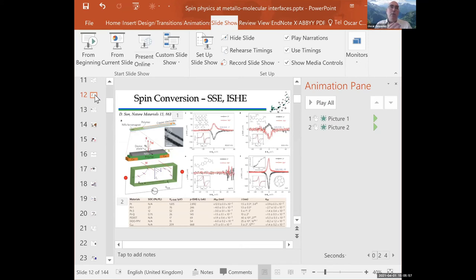However, what the simulations that collaborators have done with us point out is that it is not the Rashba dipole that is responsible for this, but a change in the electronic structure of the metal. So the metal is giving electrons to the molecule. And in addition to that, the d orbitals of the metal are hybridizing with the pi orbitals of the molecule. That is changing the electronic structure of the metal, and that is changing the spin orbit coupling splitting of the bands. That is different from the conventional understanding of spin orbit coupling as an atomic effect, the nucleus, the orbitals and the spin. But it still affects any measurement that depends on the spin orbit coupling. Does that make sense? Yeah, it makes sense.